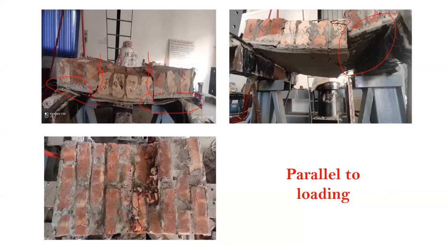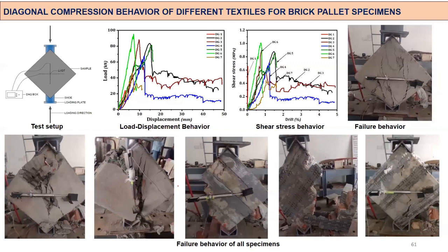Now, how can we use this material for resisting diagonal shear force? Imagine we have a wall with window openings, and the cracks will happen like this. To simulate this, we make a wall panel like this and keep the sample in the diagonal direction while applying the force, so the crack will be like this. This gives you an idea about how the material resists lateral forces. The unreinforced wall resists a force of 20 kilonewtons, whereas the reinforced wall goes up to 100 kilonewtons, five fold higher capacity, and it's a brittle failure.